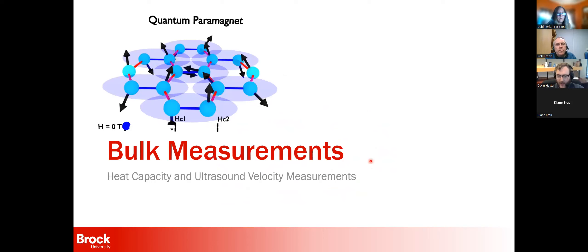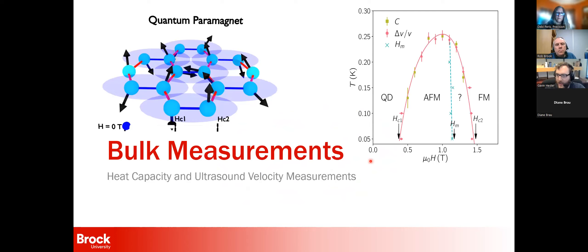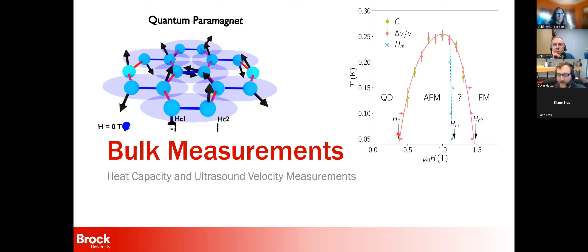I'll quickly go over our bulk measurements. Generally you first want to figure out the phase diagram — what happens when you increase temperature or field. Here is our phase diagram for ytterbium silicate for a field perpendicular to the honeycombs. At low field, we're in the quantum paramagnetic state — spins are not locked into place, no net magnetic moment, no magnetic Bragg peaks in neutron scattering. Then once you reach about 0.4 Tesla — a critical field smaller than any other Bose-Einstein condensate measured in solid-state systems like this — you suddenly break that symmetry and lock those spins into place. We classify this as an anti-ferromagnet, but it could also be called a BEC.